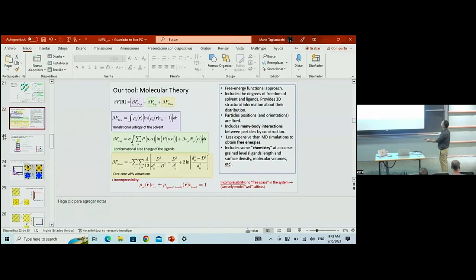First, there are a lot of things that don't show up here. For example, the size of the particle's inorganic core and the excluded volume for the ligands and the solvent basically go into the boundary conditions of this problem, which are not shown here. But that's something we can control, the size of the particle. The length of the ligand, as I said before, there is a summation here over all the conformations. We actually do have explicit conformations for the ligands, so we generate the ligands using a Monte Carlo algorithm. There you can put information like, for example, the length of the ligand.